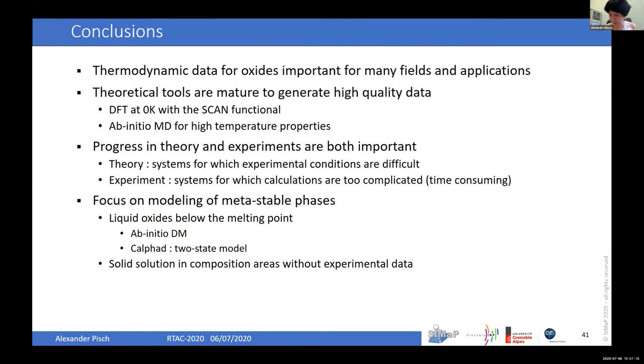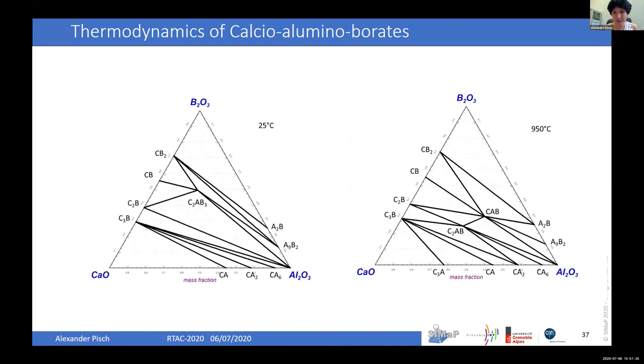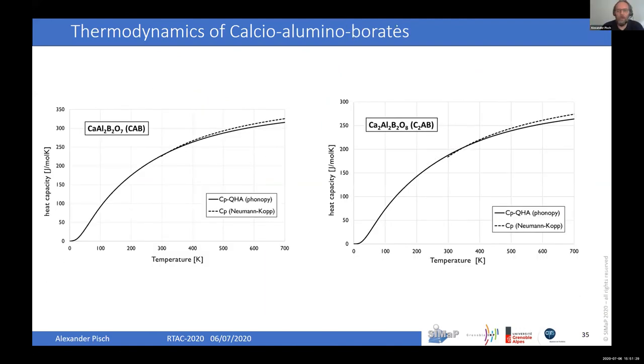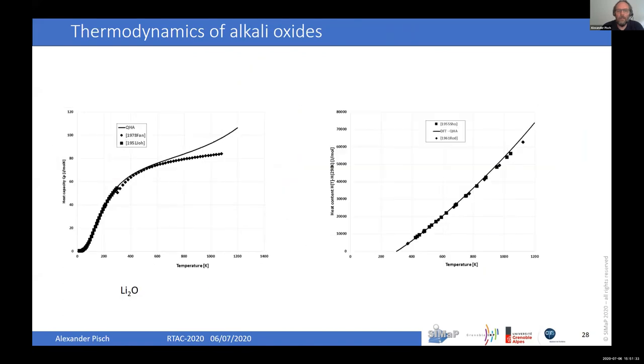Okay, I probably have one. Alex, can you go to the slide with lithium oxide? Lithium oxide, okay. There is a kind of a jump between 51 joule and 78 at, I think, about room temperature. What is the mismatch about it? I don't know where the jump comes from. I think it's just a measurement error. Okay. Because the data just started at room temperature, well, probably a little bit below room temperature, so potentially the low temperature part is not good. I don't know.